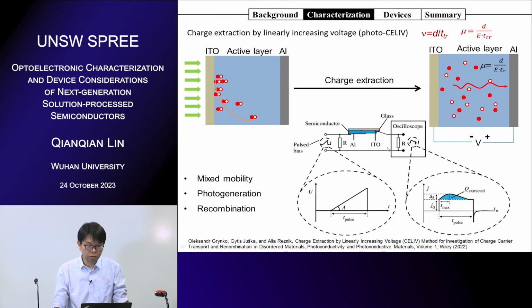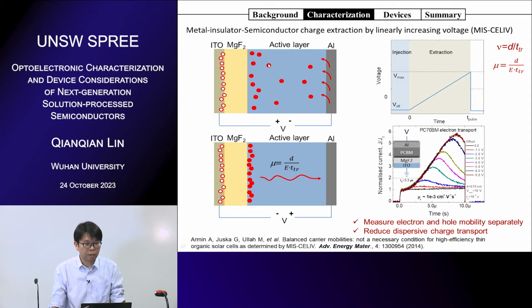For this method, it rules out the displacement current, so we do not have any effect from the RC decay, and we can see it clearly from the current transient. But for this method, we also have the problem of dispersion of photo generation, and the mobility we get is a mixed mobility, so we cannot distinguish which one is hole and which one is electron. So it's also photo generation dependent, and for highly recombining systems, the current transients are not so clear. It also affects the method a little bit. So we want to further improve the CELIV method.